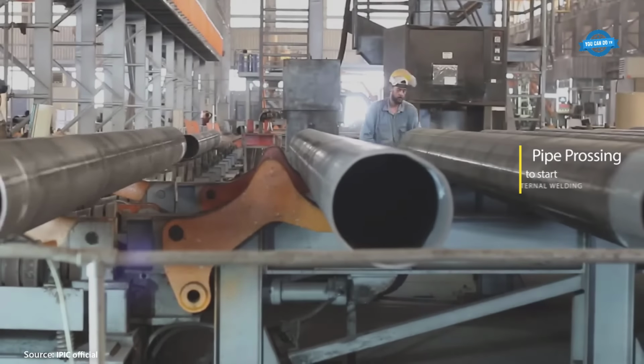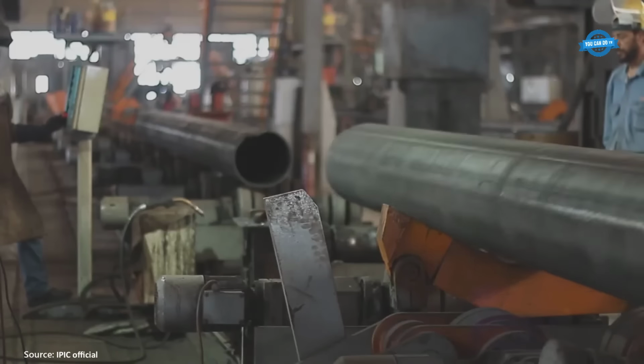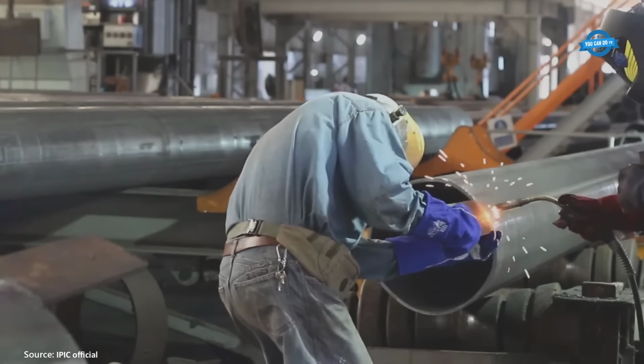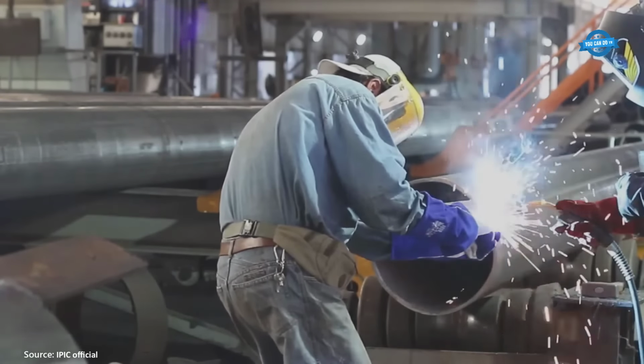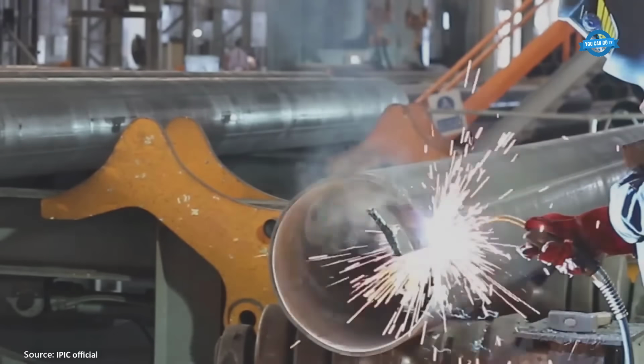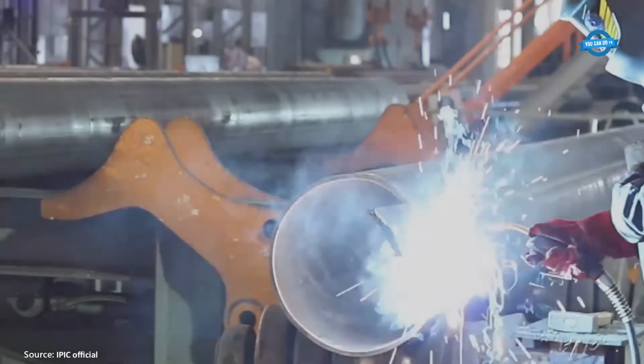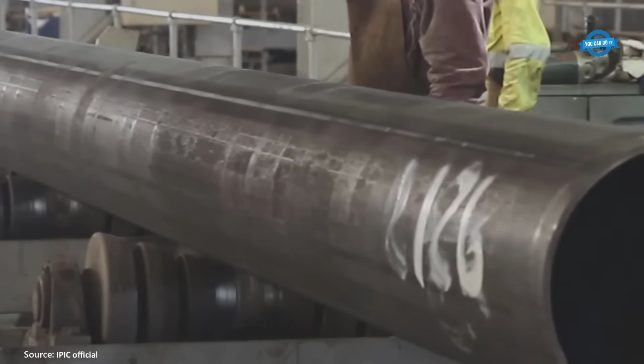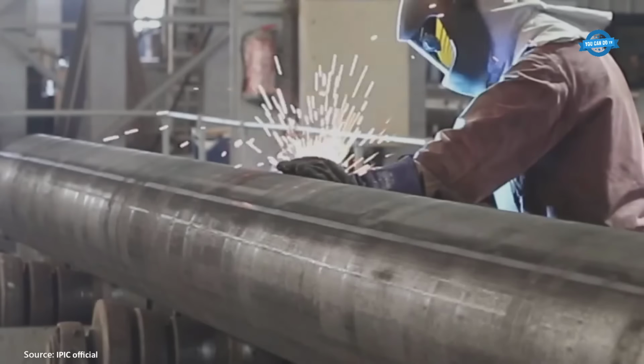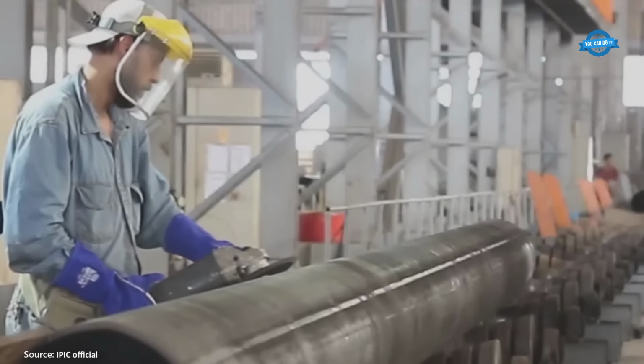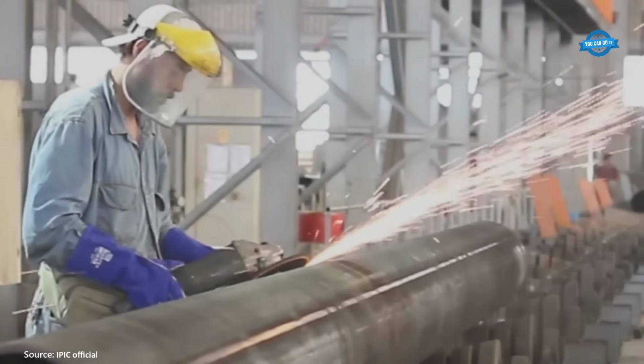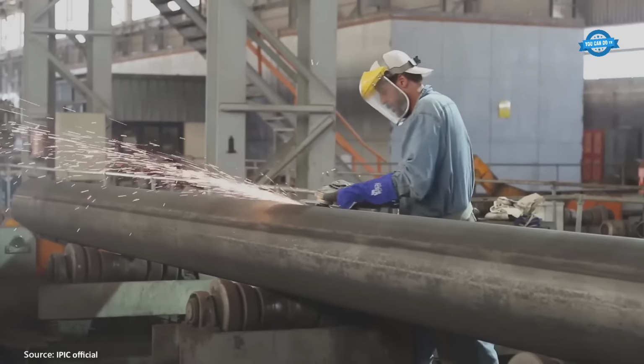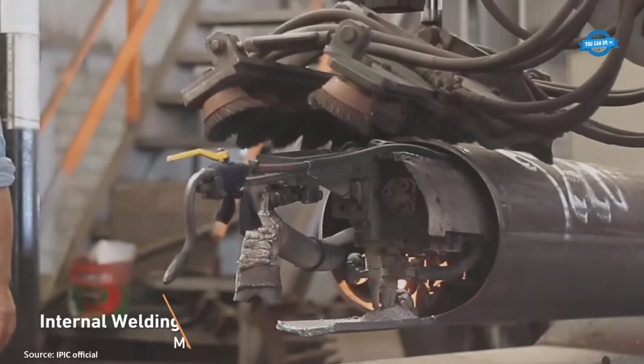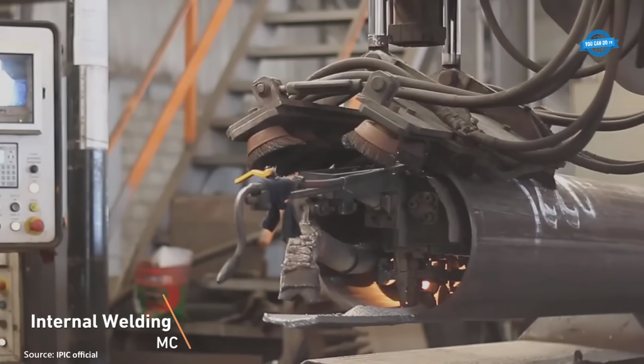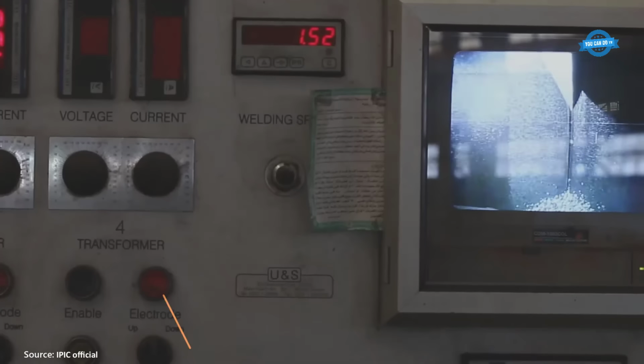Operators are stationed along the welding cells to intervene instantly if the arc deviates. These welds must pass strict, non-destructive tests, with zero tolerance for porosity. Welding wire feed speed and arc voltage are tightly regulated by automated systems. Thermal cameras scan the weld area in real time, flagging any uneven heat distribution. Weld bead shape and size are stored digitally for every pipe as part of the quality record. Every pipe is visually inspected by technicians.